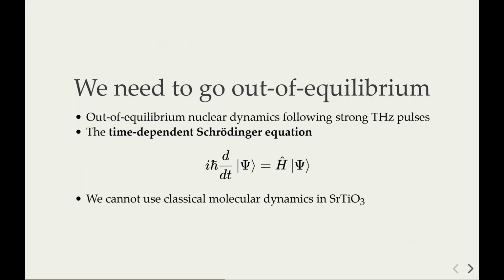So how can we perform a simulation to understand why this is happening? This is very challenging because we need the real quantum dynamics of this material, meaning we need to solve the time-dependent Schrödinger equation for the nuclei. We need quantum treatment because this material is a quantum paraelectric. If we neglect quantum fluctuations, we would get a ferroelectric anyway, because it's quantum fluctuation that stabilizes the paraelectric phase in the first place. So this is really challenging as a problem.